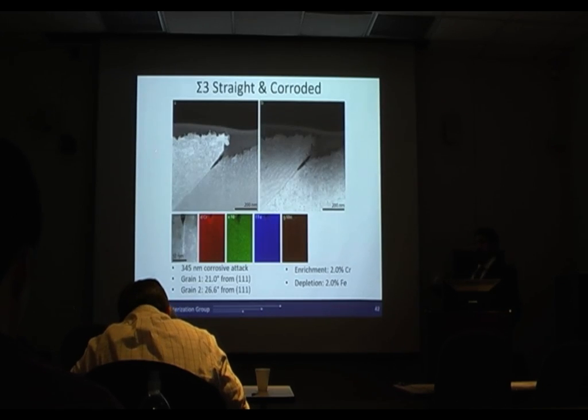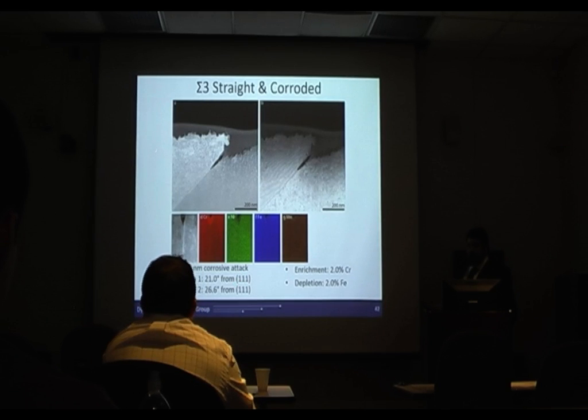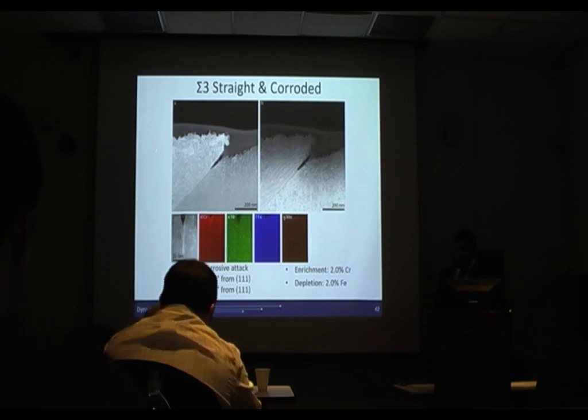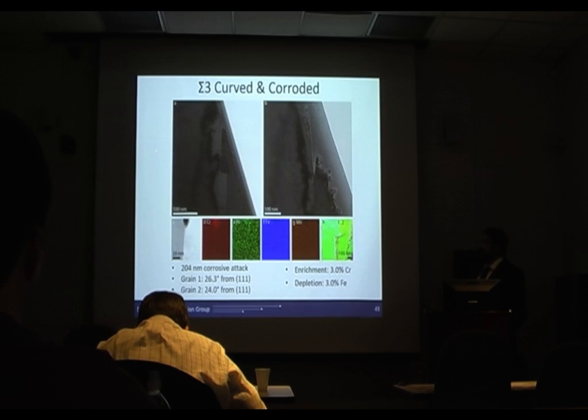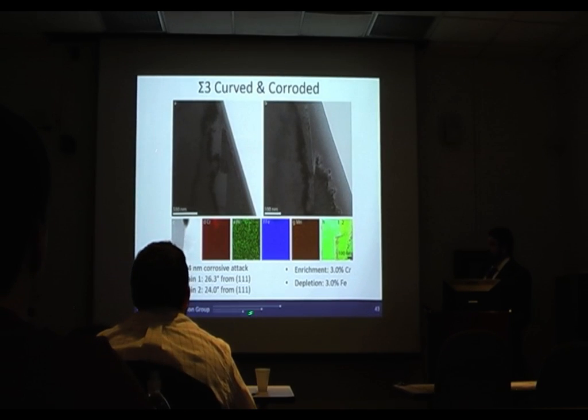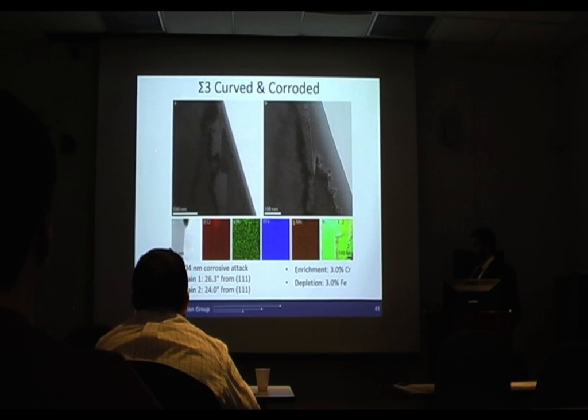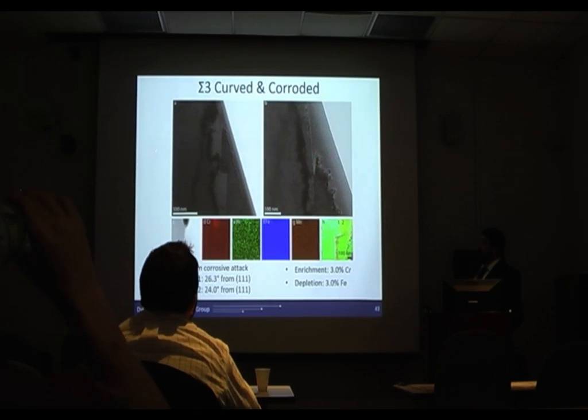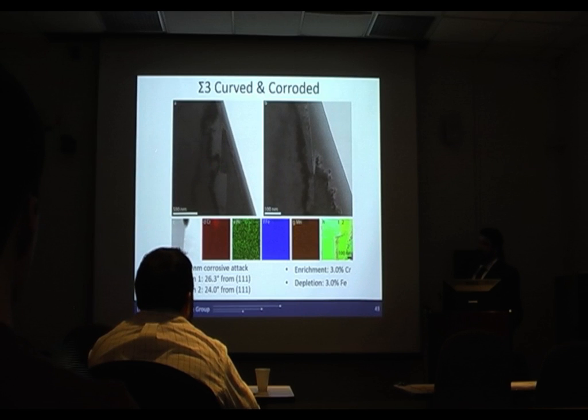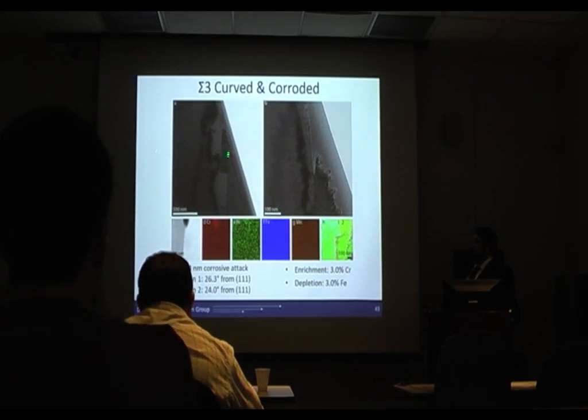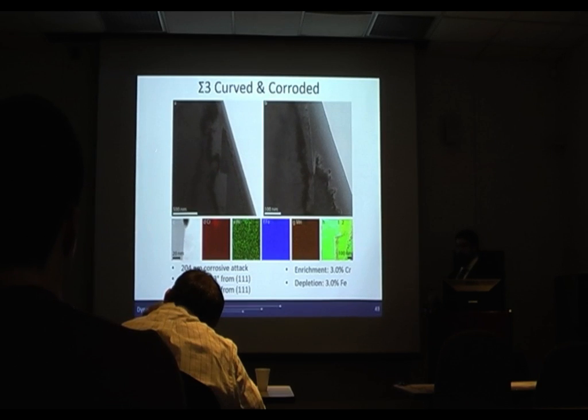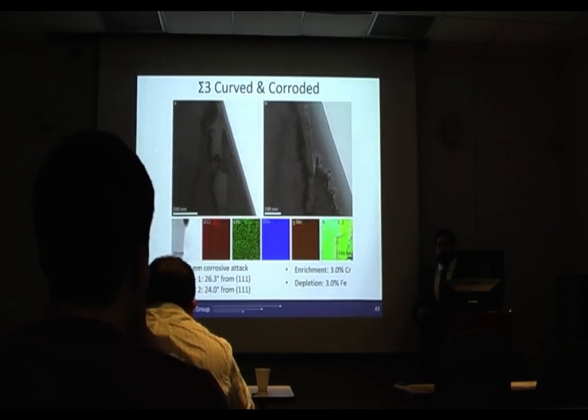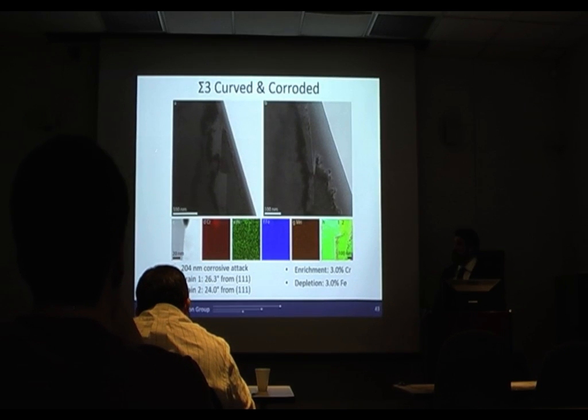When we look at one of the straight sections that did corrode, we see that we have 345 nanometers of corrosive attack, and both of the local grain boundary planes are quite far away from 111. Had, again, enrichment of chromium and depletion of iron. And then in the curved portion, again, over 20 degrees away from a 111, and 200 nanometers of corrosive attack, which you can see here. But we also see that it's not actually curved on the nanoscale. We actually have straight segments and facets. So even though it appears curved in the SEM image, it's likely the structure of these very small facets.